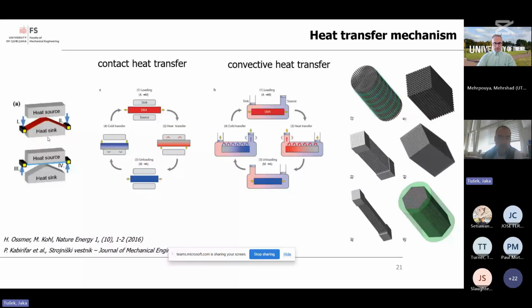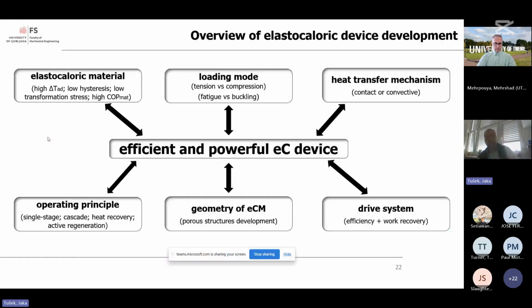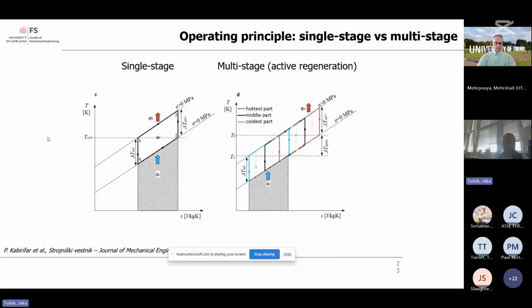Then we can of course distinguish also different operating principles from single stage to multi-stage cycles, such as cascade heat recovery or active regeneration cycle. So these thermodynamic cycles show the basic difference between single stage and active regeneration cycle. In active regeneration cycle, as you can see here, each particle of the elastocaloric material in such a porous structure performs, at the right operating conditions, its own thermodynamic cycle at slightly different temperatures, which means that you can pump heat at lower temperature compared to ambient temperatures.